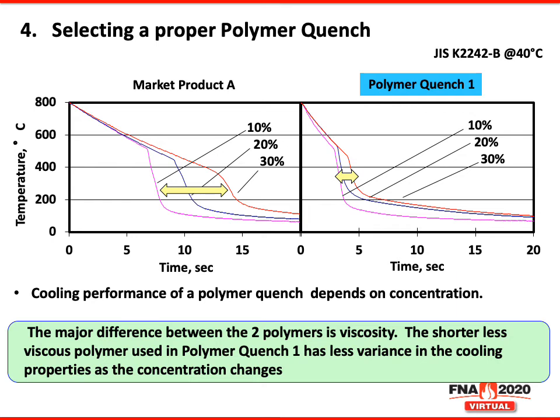We have here 3 different cooling curves for product A and polymer quench 1. You can see that with product A, not only does the cooling speed change from the red to this pink, but so does the vapor blanket stage. The difference between these two is the polymer viscosity itself.